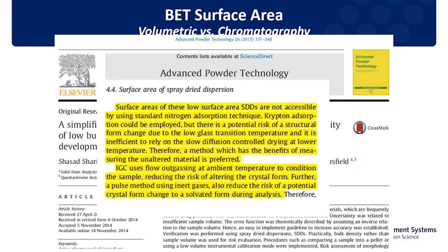So what they concluded is that for some pharmaceuticals, especially spray dry dispersions, the nitrogen technique is not suitable. So you can't measure the surface area with that technique. Krypton is an option, but there are also potential risks for structural change due to the low temperature, because when you use krypton, you still measure at 77 Kelvin.